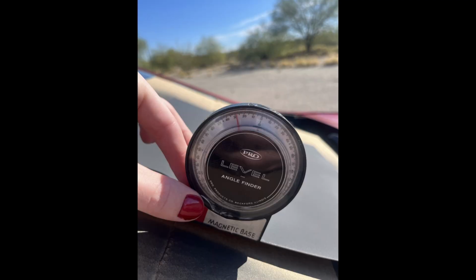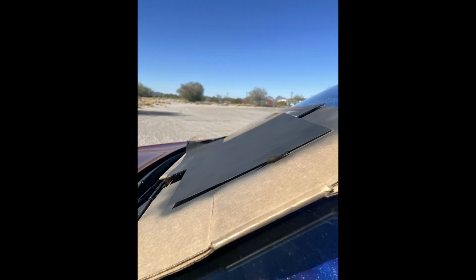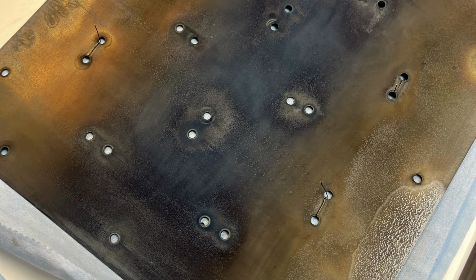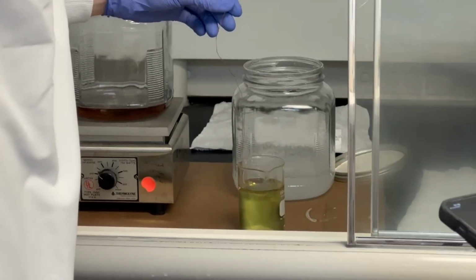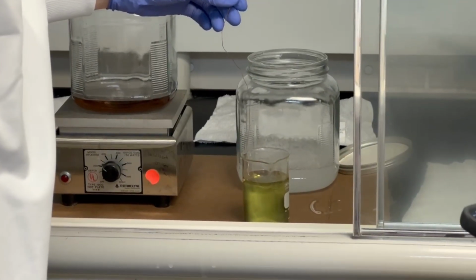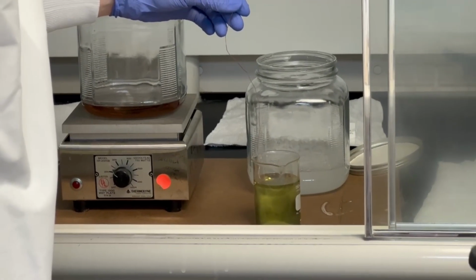Our first verification test was able to be completed with one of our prototypes, which simply stated that the difference in temperature between the panel and the air needed to be greater than 0 degrees. This test passed successfully. The aluminum panels are electroplated with black nickel, which provides a dark finish and low emissivity. This allows the panels to capture as much heat as possible while minimizing loss reflected back into the air.